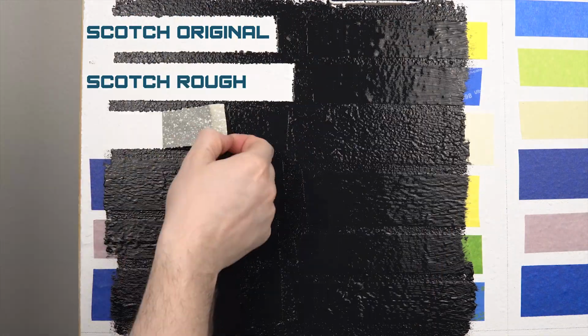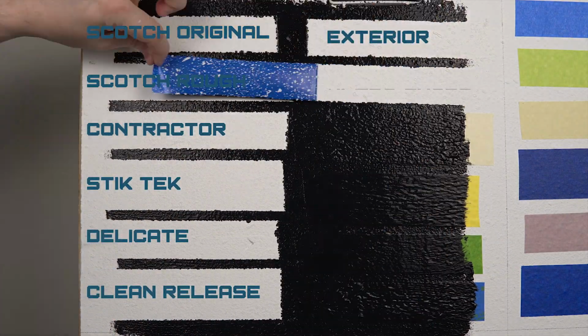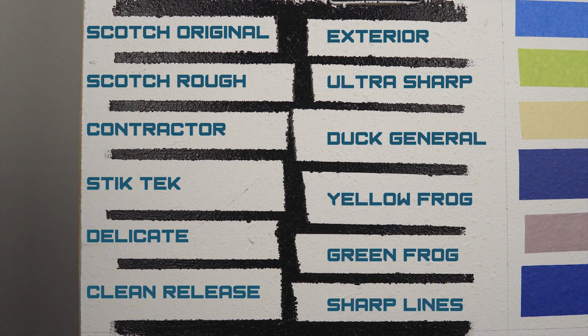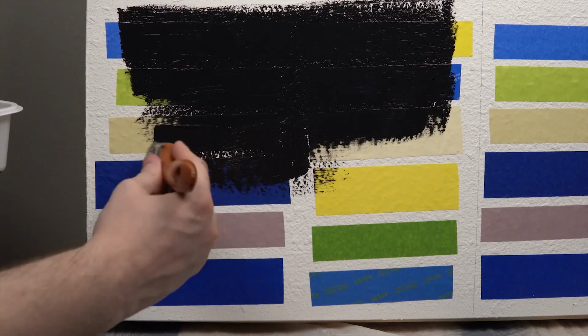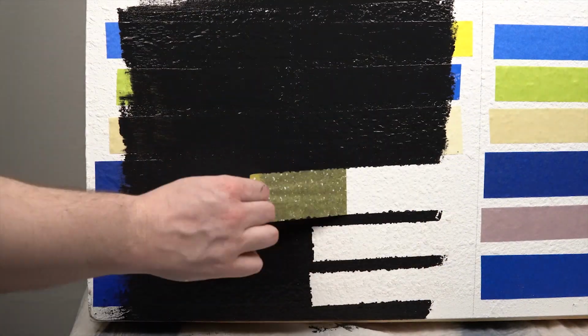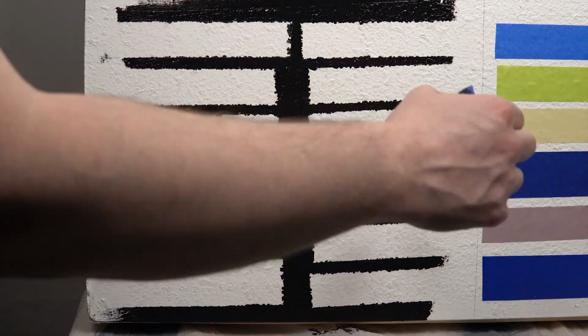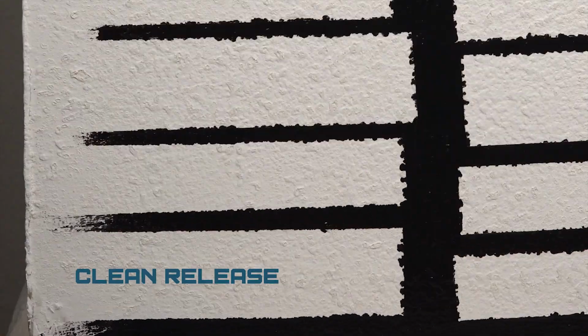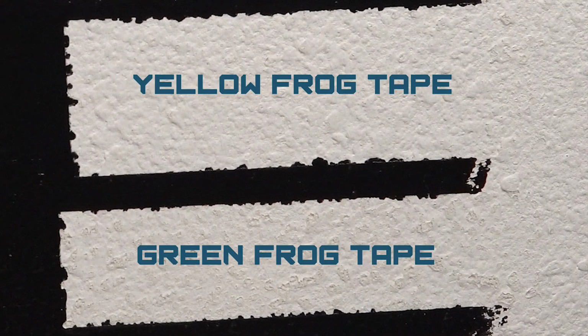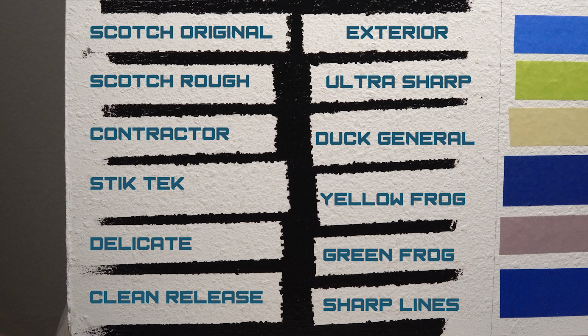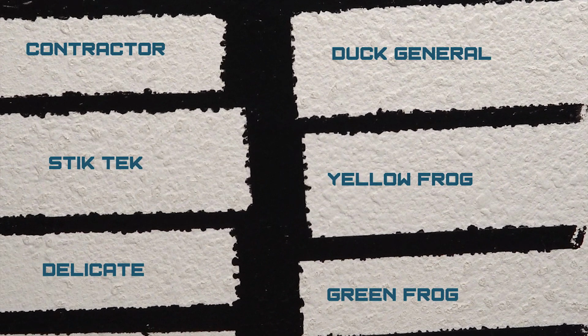For the medium orange peel texture, we can see that most of them perform about the same, with notable exceptions such as both frog tapes that had above average results. Scotch Original struggled in this test as well. For the heavy texture, the Scotch Rough Surface was expected to outperform the competition, but was only marginally better than the average. The Duck Brand Clean Release really impressed on this test, while both frog tapes somewhat struggled. One important note here though was that the Delicate Surface frog tape was the only one to cleanly release from the wall without pulling paint or texture from it.